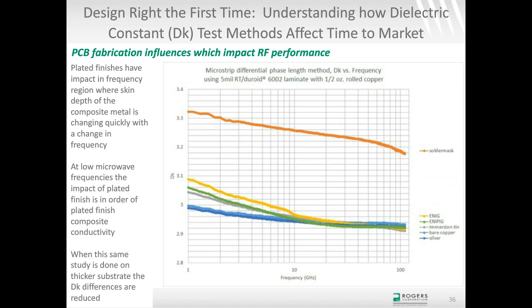And what I mean by that, at very low frequencies for ENIG, electroless nickel, immersion gold, you actually have the composite conductivity of copper, nickel, and gold. And then as you go up in frequency higher and higher due to skin depth, now you have a composite conductivity of nickel, gold. And as you go much, much higher, then you have a conductivity mostly of gold. So that's what's happening at the lower frequencies. As you're changing frequency and the skin depth is changing, the composite conductivity is changing,